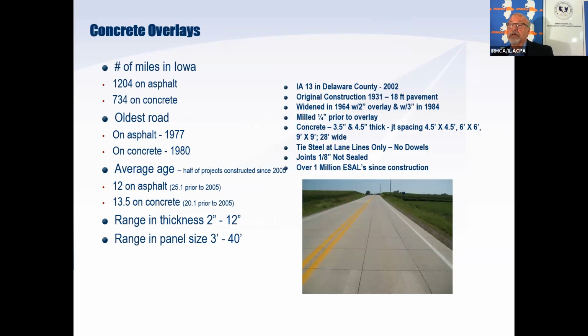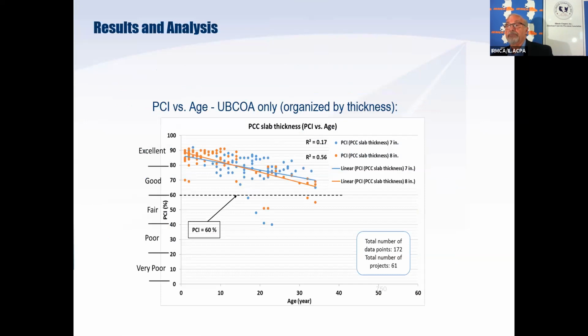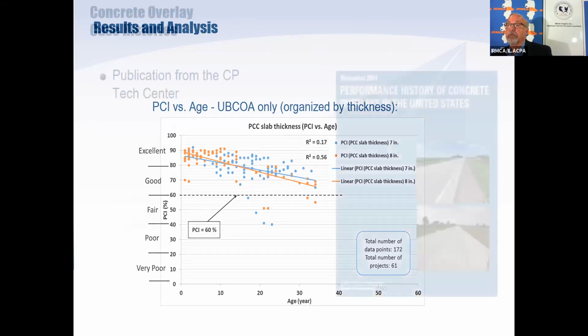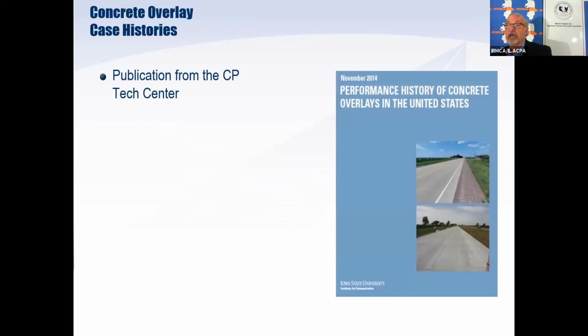The oldest in Iowa is 1977 on asphalt. On concrete was 1980, 2 inches to 12 inches, with panel sizes from 3 feet to 40 feet. We've used that in great measure to do the overlay guidebook that I referenced before. So this is the results in the analysis. I know that is somewhat difficult to read, but the bottom line is that the vast majority of the overlays, regardless of age in Iowa, regardless of the thickness and the type of overlay, are still good performing. There's the case history publication that you can download from the CP Tech Center as well, and it's worth looking at.